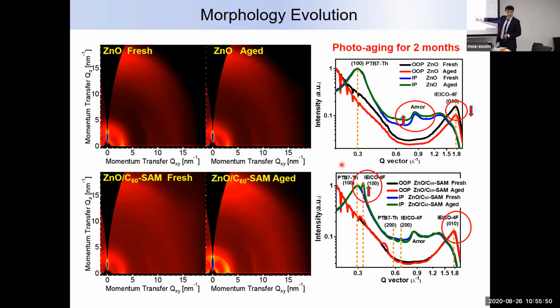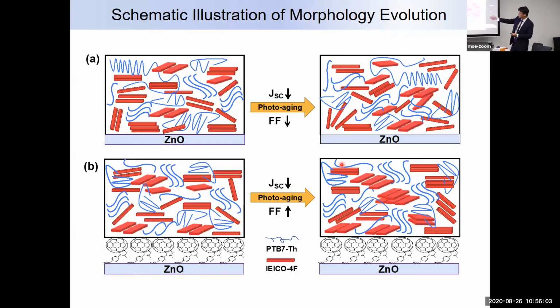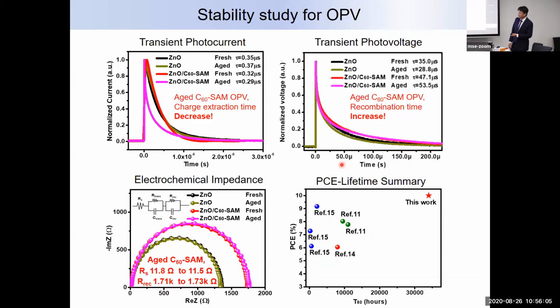But when we crystallize, we reduce a little bit of the interface. That's why we get the current decrease until they kind of plateau out. Okay, so this is another strategy that we can use to increase the OPV lifetime. And this is now the longest lifetime with decent performance.